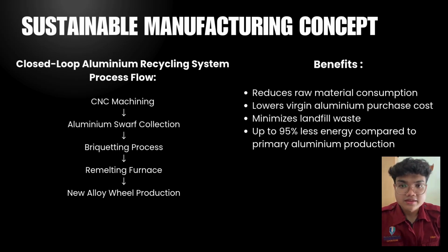To improve sustainability, a closed-loop aluminium recycling system is proposed. During CNC machining, aluminium chips known as swarf are generated as excess material is removed from the wheel blank. Instead of disposing of this waste, the aluminium swarf can be collected and compressed through a briquetting process before being returned to the melting furnace. The recycled material can then be reused in the production of new alloy wheels. This approach provides several benefits, including reduced raw material consumption, lower purchasing costs for virgin aluminium, reduced waste sent to landfills, and significantly lower energy requirements compared to producing aluminium from raw ore.